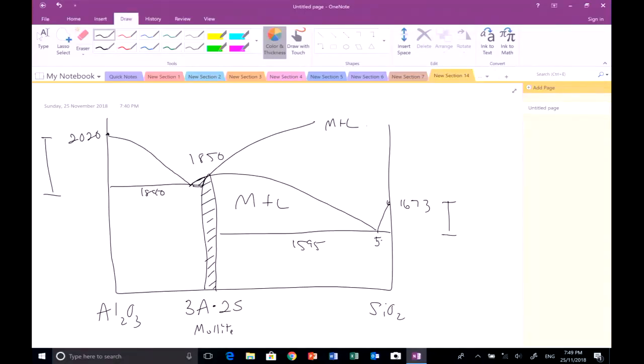If your composition is slightly alumina-rich, you're going to have problems doing liquid phase densification, for two reasons. First, the required temperature is much higher. And the second is the flexibility that you have in terms of composition and temperature is very small. And these are naturally occurring raw materials, so they vary. You could very easily find yourself outside of that two-phase region, and then you get complete liquefaction, or you don't get the right phase. You don't get liquid phase densification.